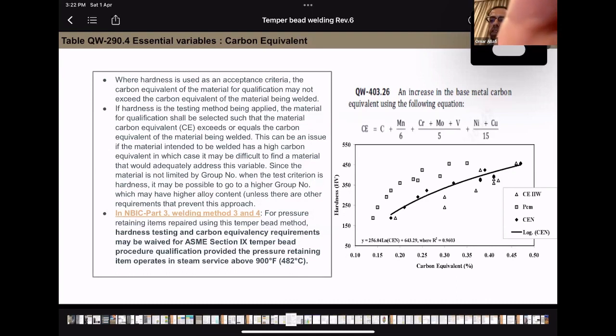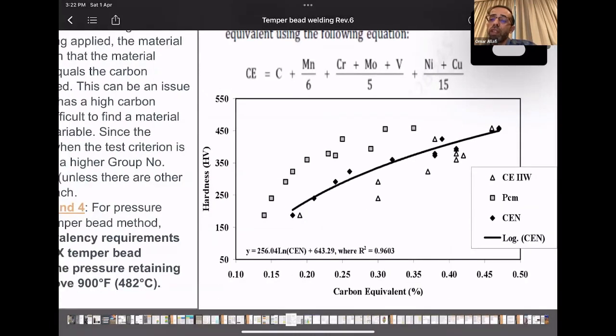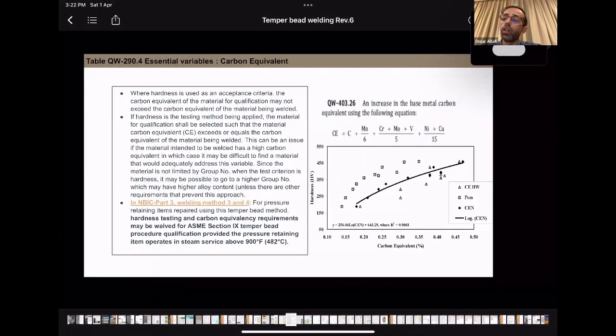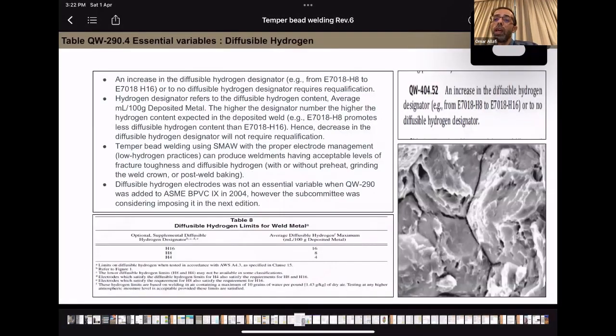And again, this is an essential variable only for when hardness is specified. As we can see here in this chart, how carbon equivalent can affect the hardness values. So the higher the carbon equivalent, the higher the hardness you will get after welding. And diffusible hydrogen is another concern. So this is also an essential variable for both of them, for toughness as well as hardness.